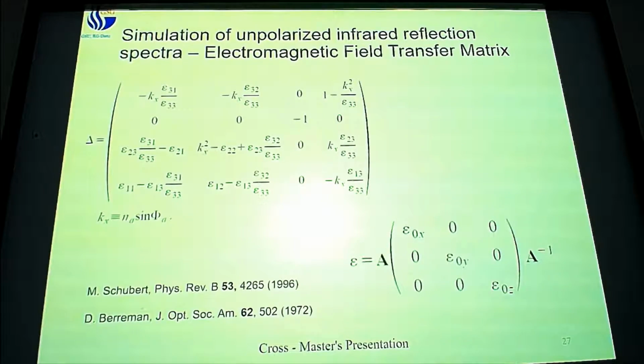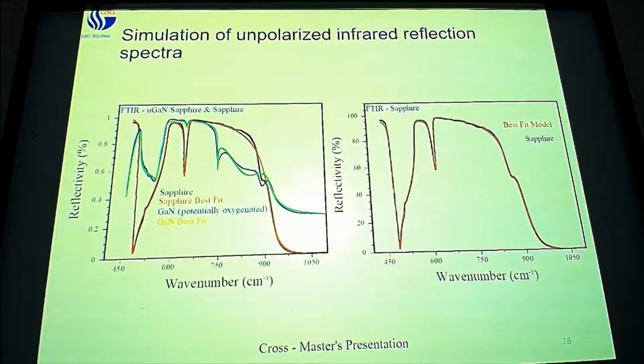All of this feeds together to make some fits. Originally, I was using a 2x2 method, which took just the parallel components of my light, if I remember correctly. So I didn't bother with the perpendicular components of the polarization. And that left us with a couple of points where there was no good fit. You can see here, I have a black line and a red line. We're talking about sapphire specifically. Here, there's a section where it deviates, and there's a section where it deviates here, and correspondingly there.